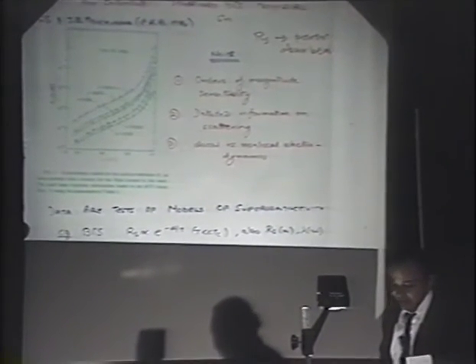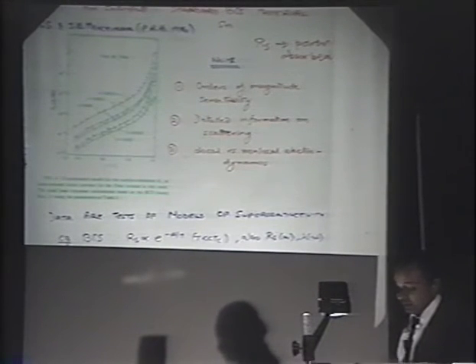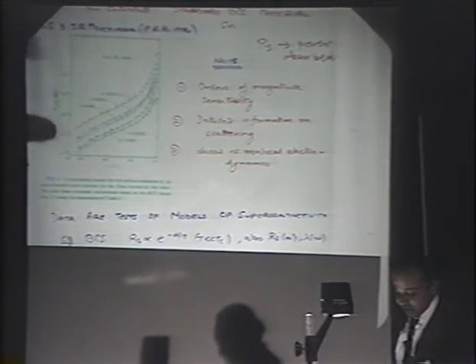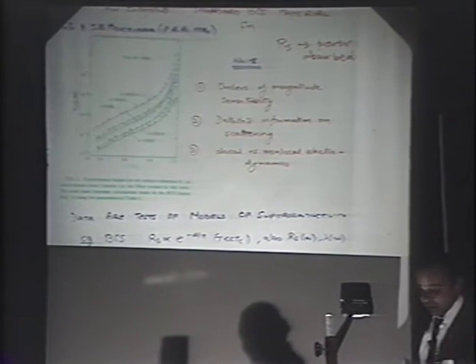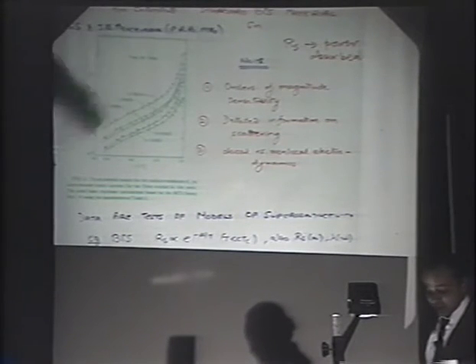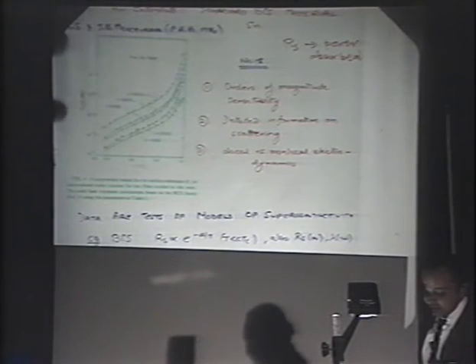Since this measurement is unfamiliar to most people, let me give you an example of a standard material like tin, on which I did some measurements some time ago, and the kind of information one can get. What one measures is the surface resistance, which is proportional to the microwave power absorbed by the superconductor. This is a plot for tin of log of RS versus reduced temperature, covering orders of magnitude. The points are experiment. The dashed line is BCS theory. The agreement is excellent. The point is that if properly done, one can get orders of magnitude sensitivity and